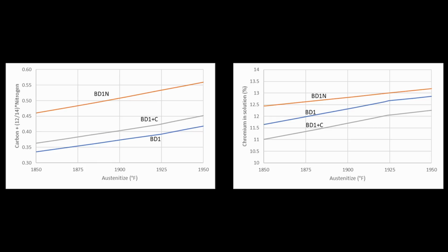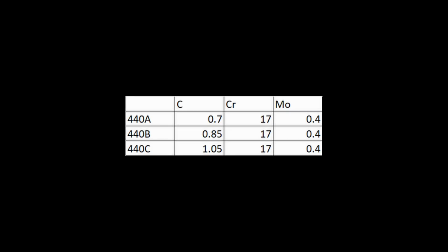Mysteries unveiled. Yeah, and earlier I said BD1 is basically a 440 series stainless. So 440A, B, and C show this same effect. Those are the same steel with 17% chromium. And then 440A has 0.7 carbon, 440B is around 0.85, and 440C is around 1.05. And so as you go up in carbon, the potential hardness of those steels goes up, but the corrosion resistance and toughness goes down. So yeah, if you want high wear resistance and high-ish hardness, 440C is the choice, but its corrosion resistance is not as good as 440A. So the nitrogen in this case with BD1 and BD1N, it's kind of like, oh, we just make everything better, almost.